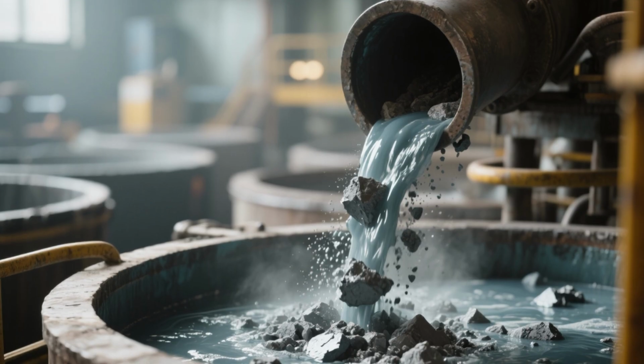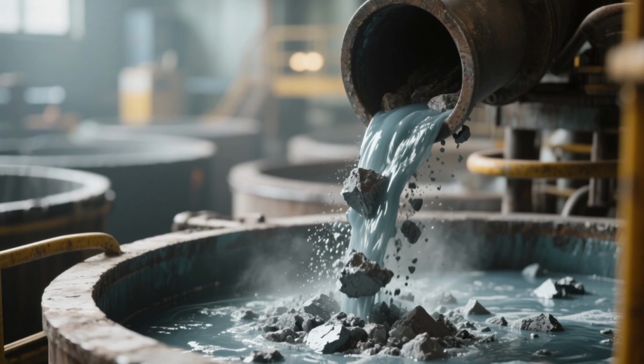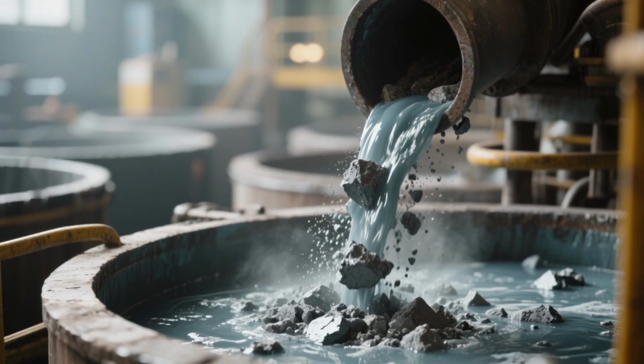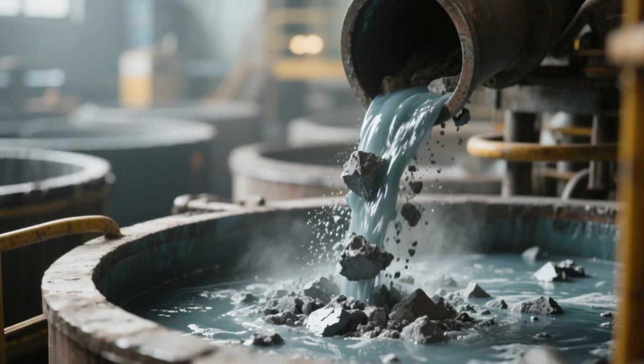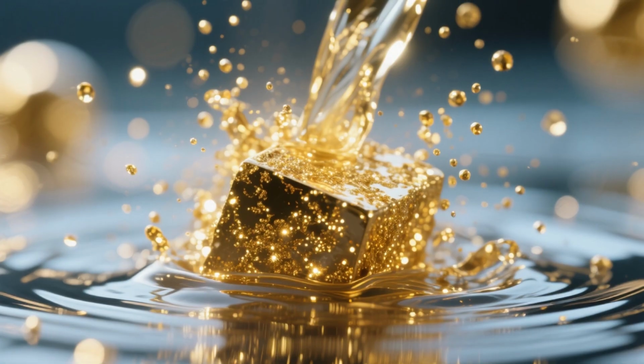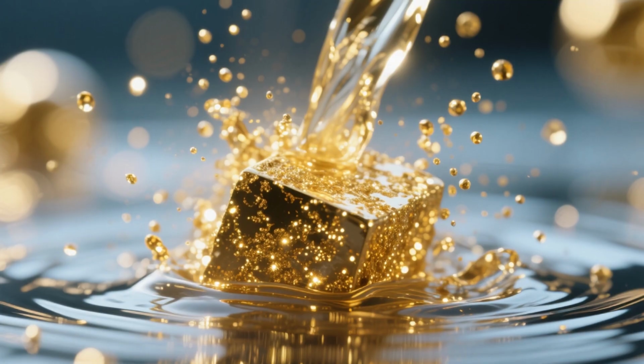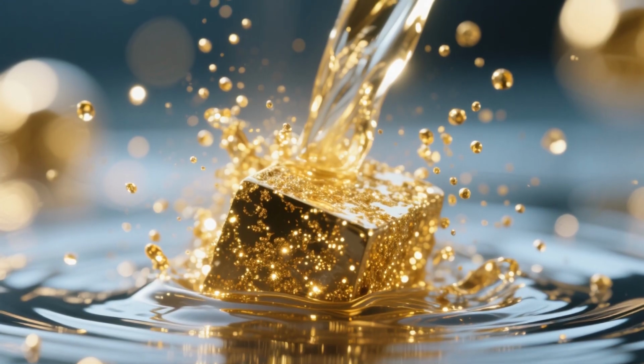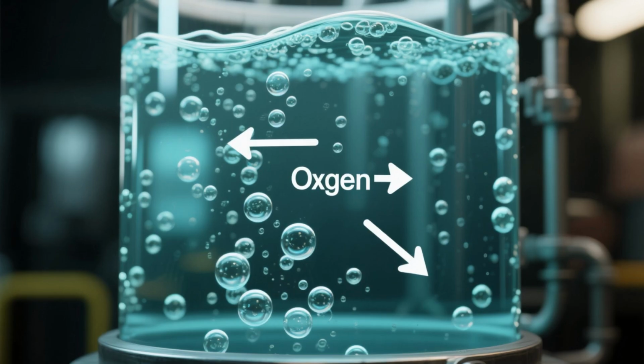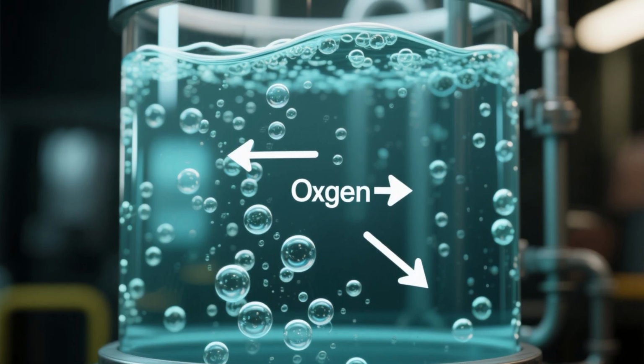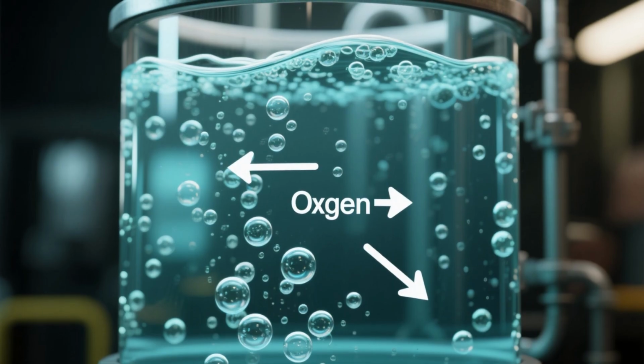The calcine, or treated concentrate, is moved into large tanks and mixed with a very weak solution of sodium cyanide. Cyanide has a remarkable chemical affinity for gold. It latches onto the gold particles and dissolves them, pulling them out of the solid material and into the liquid solution. This forms a chemical compound called a gold cyanide complex. To speed up this reaction, air or pure oxygen is continuously bubbled through the tanks. The entire leaching process can take anywhere from 24 to 72 hours.